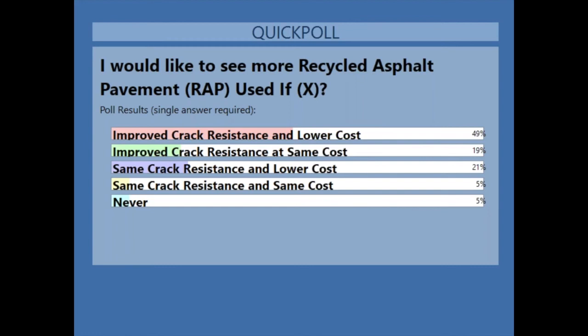And you promised us all of these things up above, right? Reduce cost of the asphalt pavement, reduce amount of virgin binder use, maybe even reducing the amount of modification. Reduce the needed aggregate used, pave more roads with the same budget, reduce the mountains of RAP. It's going to require less CO2 emissions, a greener solution. But guess what happened when a lot of states went from 10 or 15% RAP up to 50% RAP? They immediately had crack performance problems. And the reason for that is, guess what? We made the mixes too stiff.